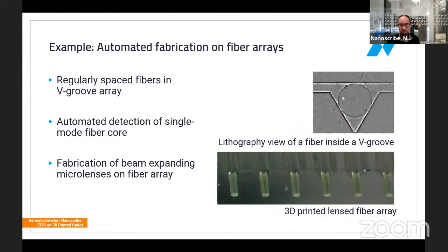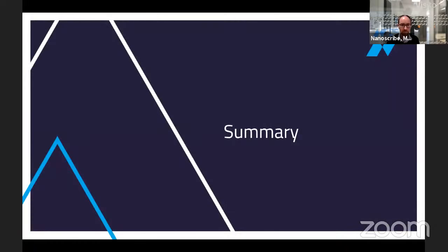Or you can print on fibers and fiber arrays. Here you see a V groove, and our system allows for automatic recognition of the fiber core, alignment, and printing thereof in order to print MicroOptics, which relax the mode field diameter.